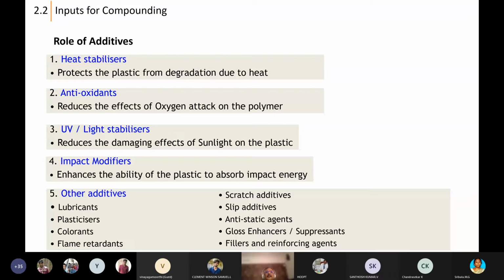What happens is that it is not that they will continuously be resisting fire. A lot of testing methods have evolved, like Underwriters Laboratories has come up with UL standards. Okay, you expose the plastic to fire for a particular time, say 30 seconds. Then you withdraw. You expect the plastic to extinguish on its own. Then you call it a flame retardant. Again, there are ratings like UL V1, V2, V0, depending upon how much time it takes to extinguish. Any plastic that extinguishes immediately comes into the category of V0 or 5V, which are considered very good.